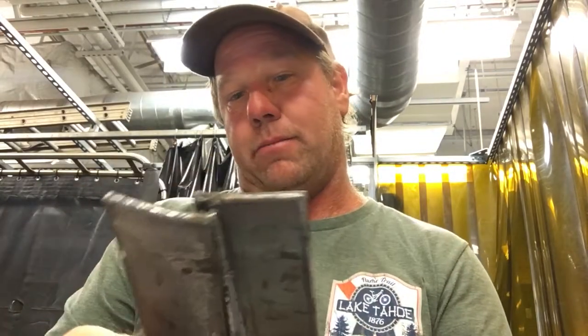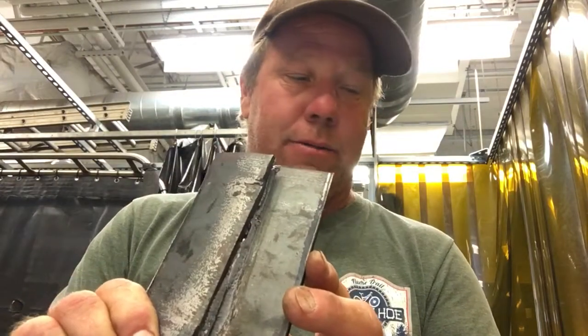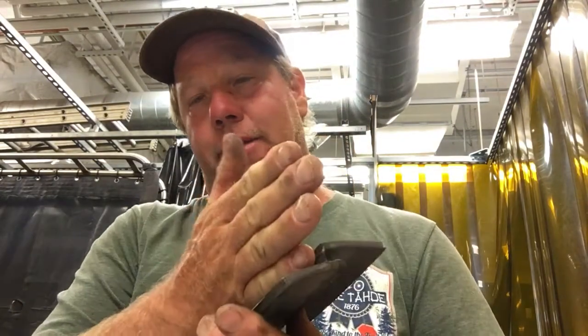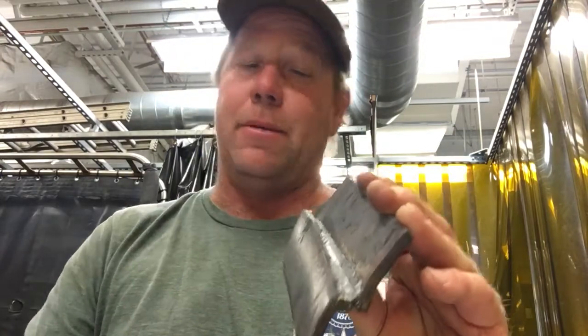Commonly, you come up with a product and you're saying, I'm going to make this product in X, Y, and Z in this sort of pattern, this way. And then you make it, and then you test it. So I'm saying, look, this weld's strong enough that I can put a great deal of force. This weld is actually designed to fail, by the way. These two come together. There's an open crack, and when I push down, it just lifts that crack up. If I were to weld this back edge together, this wouldn't happen. Or if I had a full penetrating weld, that wouldn't have happened either. So this weld is actually designed to fail. It's called the fillet break.